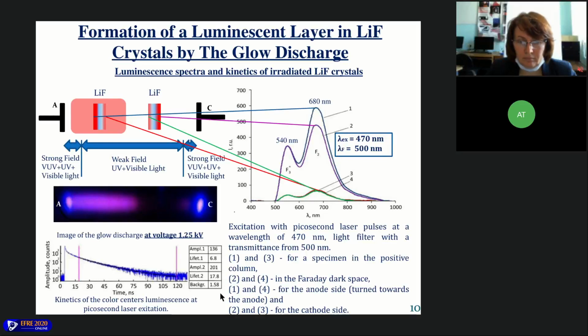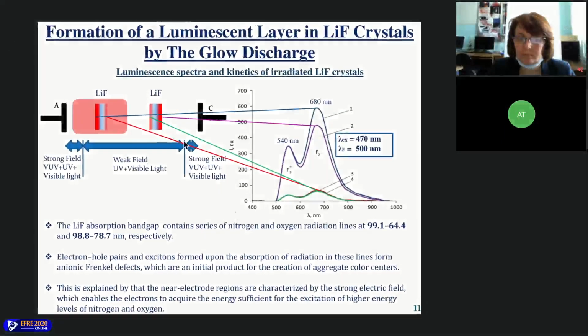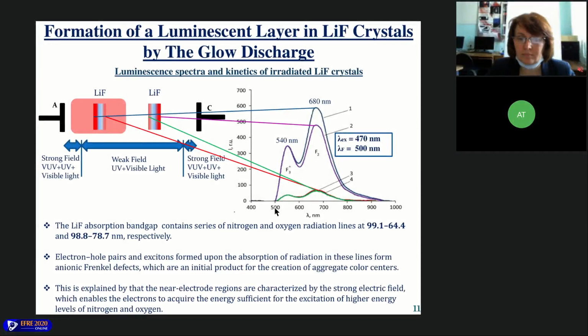The high concentration of luminescent defects corresponds to the side of the crystal facing the electrodes, curves 1 and 2. You can see it here, it's a red gradient in here. And the smallest defect concentration corresponds to a low intensity of vacuum ultraviolet radiation in the dark Faraday space. So next slide, slide number 11.